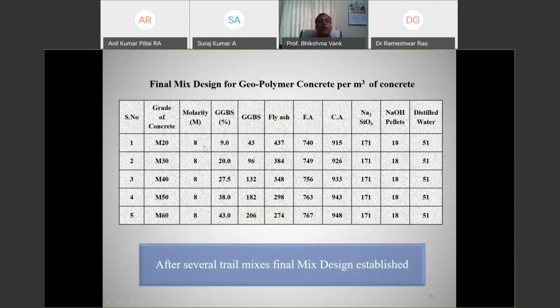For GGBS, for M20 it is 9%, for M30 it is 20%, M40 is 27.5%, M50 38%, and M60 43%. As the grade is increasing, the GGBS increases, and these grades we have established actually. Earlier, geopolymer concrete grades were not there. So with 8 molarity, we have obtained the target strengths with these mix proportions after several trial mixes.